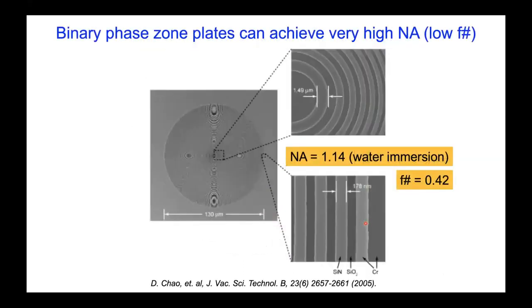Now, of course, this is a fairly old idea, more than a century old. I just picked some work that we did many years ago, where we showed that one can design binary phase zone plates, which have been around for over 100 years, but can be extended into numerical apertures larger than 1. Of course, in order to do that, you need to go beyond air. So in this example, we exploited work done in microscopy to do a water immersion lens, where such a zone plate was fabricated in silicon nitride.